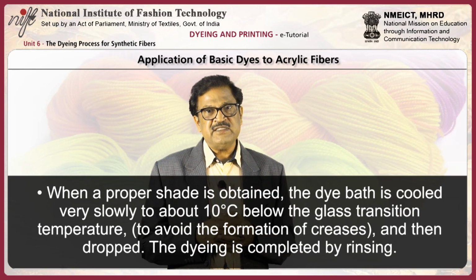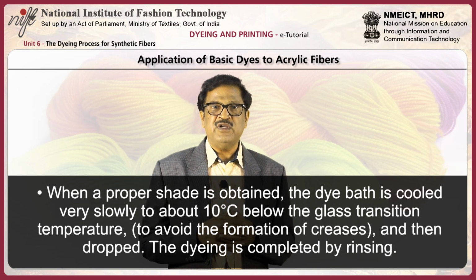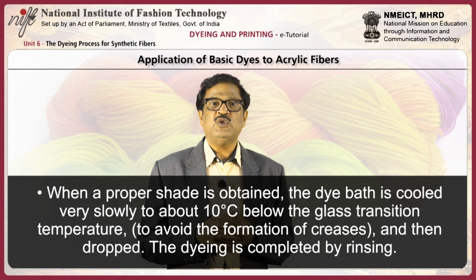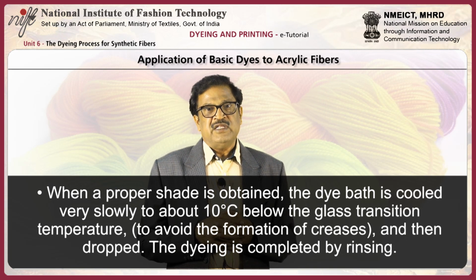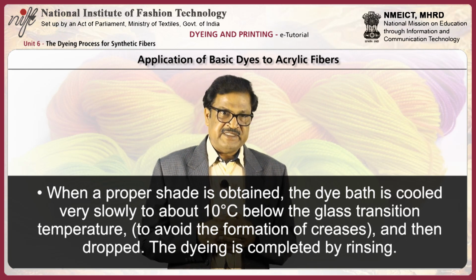When a proper shade is obtained, the dye bath is cooled very slowly to about 10 degrees centigrade below the glass transition temperature to avoid formation of creases, and then dropped. The dyeing is completed by rinsing.